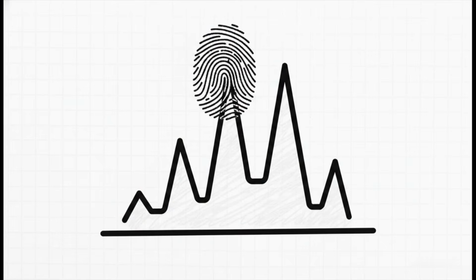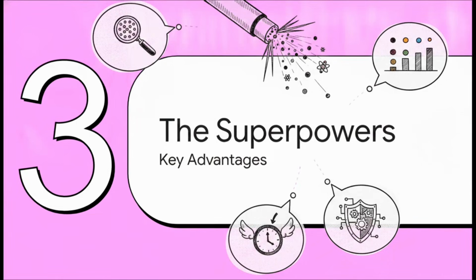Because every element has a totally unique atomic structure, every element emits X-rays at incredibly specific energy levels. When you look at an EDS spectrum, you'll see sharp peaks at different energy levels, which are measured in kiloelectron volts. A peak at one specific spot means, without a doubt, carbon is present. Another peak definitively identifies oxygen, or magnesium, or gold, or silicon. The detector counts these X-ray hits, and that lets us map out precisely which chemical fingerprints are hiding in our nanomaterial. Which brings us to part 3, the superpowers, key advantages of EDS with FESEM.